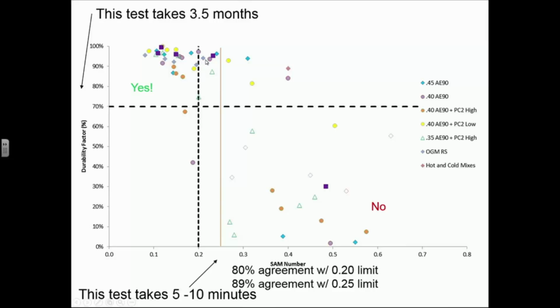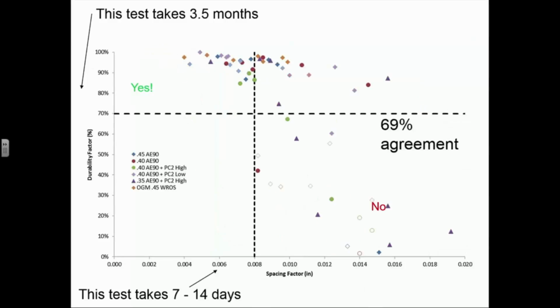But look. There's several of these mixes that go past this 0.20 to a 0.25. If we move this limit to 0.25, we get an 89% agreement between this upper left quadrant and the lower right quadrant. You'd say, well, how did you know? Well, remember, we established the 0.20 limit based on a spacing factor of 0.008. That was the original work that we did. And I don't regret any of it. But we do spacing factor measurements to find out more information about freeze-thaw durability. I mean, freeze-thaw durability is the real indicator of what we care about. And here's a whole lot of data that's showing us that, guess what? For freeze-thaw durability, a little bit higher SAM number. And actually, if you go back, I don't think that's unreasonable. People for a long time have seen that sometimes a spacing factor of 0.008, although conservative, can sometimes be adjusted a little bit.